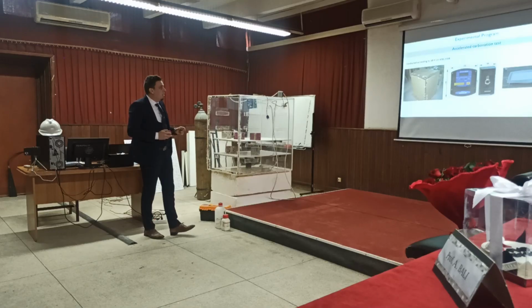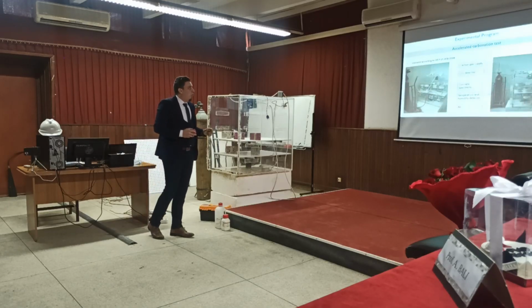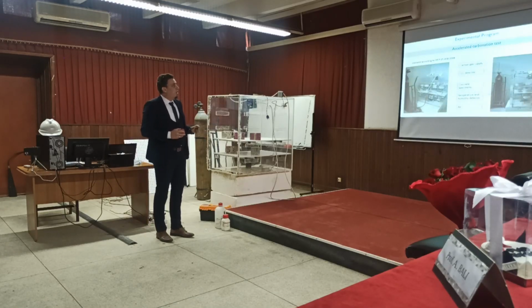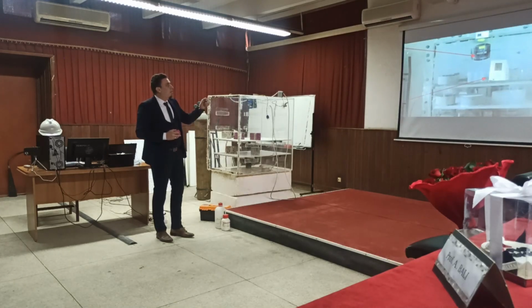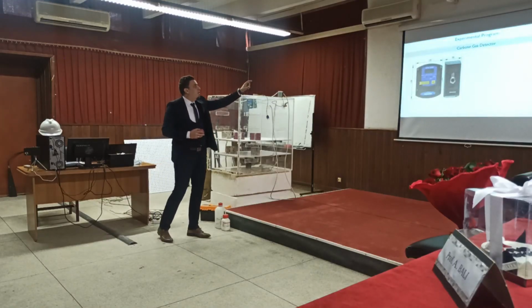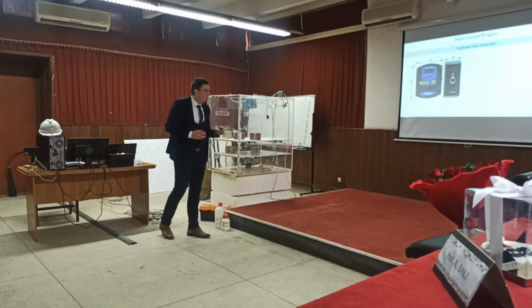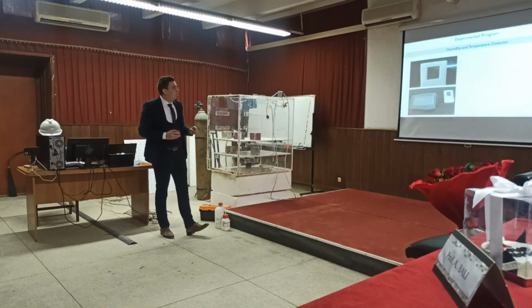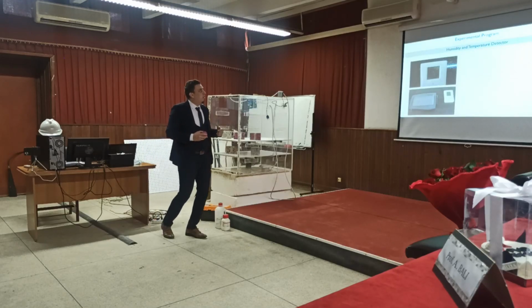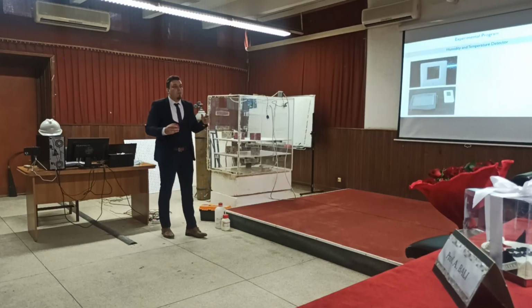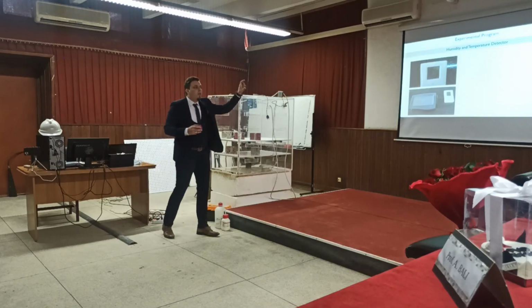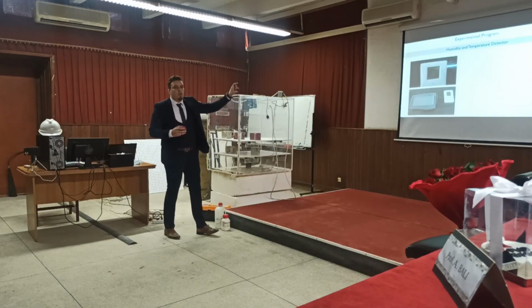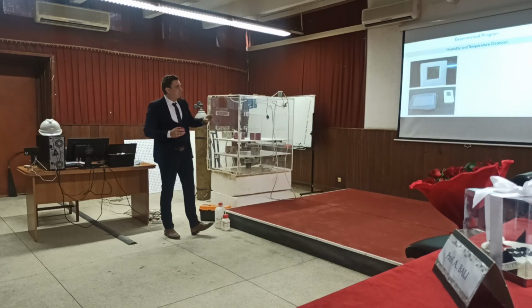After 2 years, we manufactured our experimental chamber. The important devices are the regulator of the gas pressure and the carbon dioxide gas detector. We use this gas detector, and for humidity and temperature, we use this device. Why? Because we should ensure the required humidity and temperature following the standard.